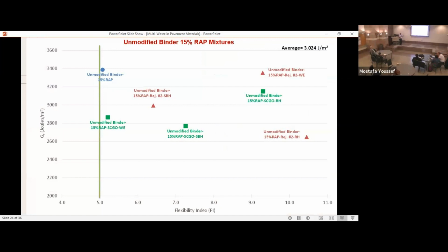Let's look at this map. Our blue dot here is our binder with 15% RAP. That's the control. It is right at the edge of acceptance. As you add the rejuvenators, and even add the rejuvenators with the ash, your value continues to increase. Looking at the fracture energy, the bandwidth is about the same, but what is happening is you're increasing the flexibility through slowing the rate of crack propagation. The green dots represent the combination of ash with our rejuvenator. The red dots represent the ash with the second rejuvenator. We dropped one of the rejuvenators based on the mastic results. So in this phase, we're only doing two rejuvenators, the food waste oil and another one, and dropped rejuvenator number 1 based on the mastic results.